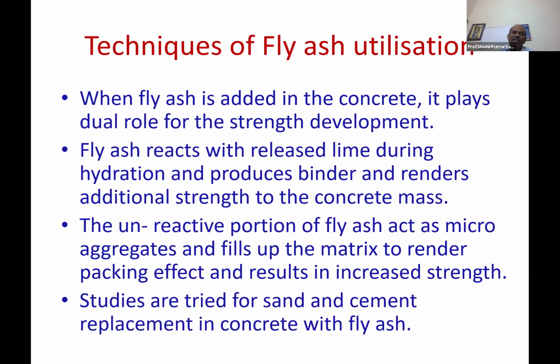The techniques of fly ash utilization. When fly ash is added to concrete, it plays a dual role in strength development. Fly ash reacts with the released lime during hydration and produces binder, which renders additional strength to the concrete mass. So fly ash gives additional strength. The unreactive portion is also used as a filler of the matrix to give a packing effect, resulting in increased strength. Both ways it is helpful. Studies are tried for sand and cement replacement of concrete with fly ash.